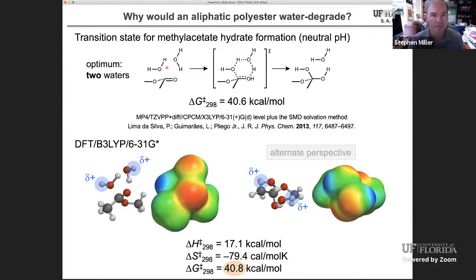Of course, you can hydrate with just one water molecule. That'll have a higher enthalpy barrier, but a lower entropy barrier because you only use one molecule. Computationally, the sweet spot is to use 2 molecules of water. You have this relatively enthalpically favorable 6-member transition state. Of course, you have to bring 3 molecules together to accomplish that. So this barrier is fairly high, 40 kcal per mole for delta G double dagger, which means it's really not going to happen at room temperature, which is why you can use methyl acetate near water and nothing happens, or at least one of the reasons.